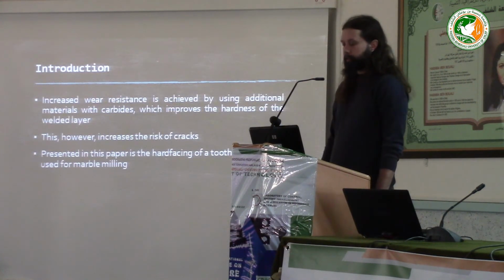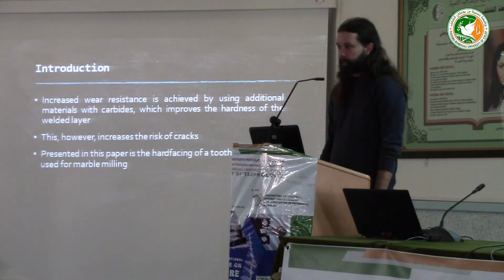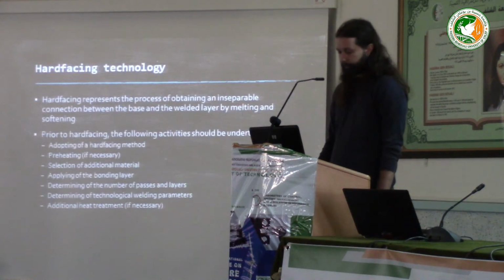Now, in order to increase the wear resistance of a machine part, additional materials typically should have a high carbide content, which will improve the hardness of the welded layer significantly. However, the presence of carbides, in our case tungsten carbides, also increases the risk of cracks occurring and propagating through these carbides. In this paper, we will present an example of hard facing of a tooth of a marble milling machine, where the goal was to weld an additional layer with a thickness of 6 millimeters on top of an existing tooth in order to improve its hardness and therefore wear resistance.